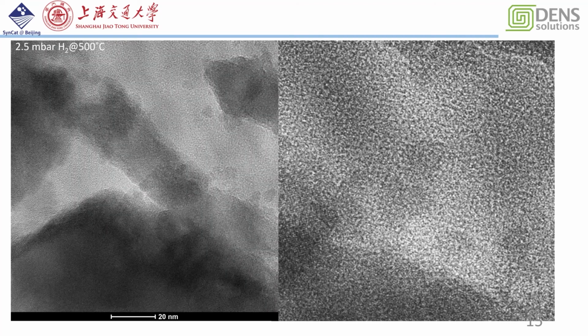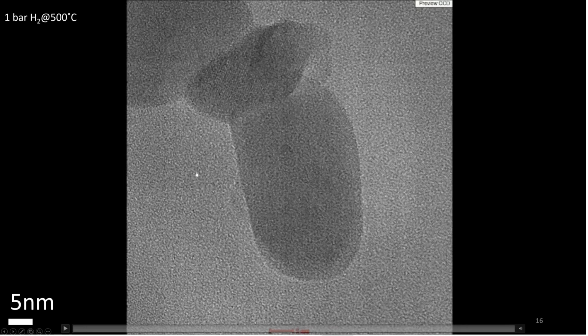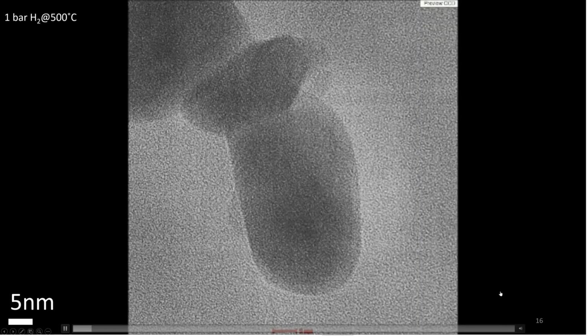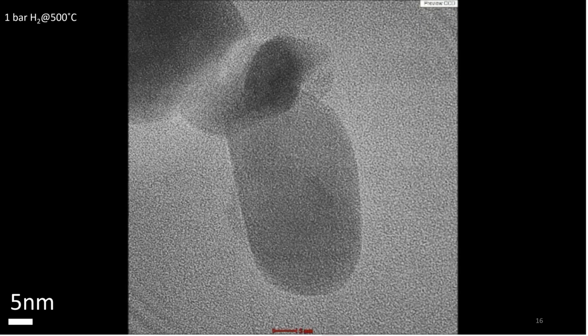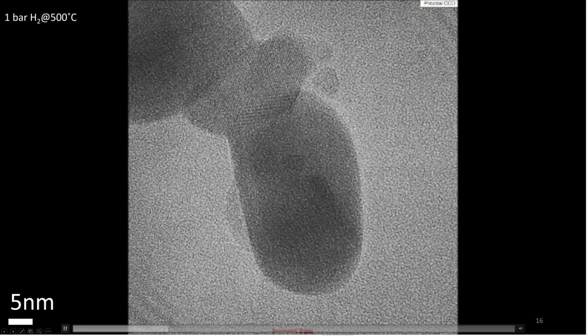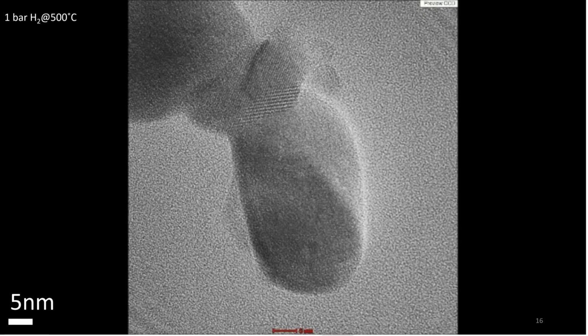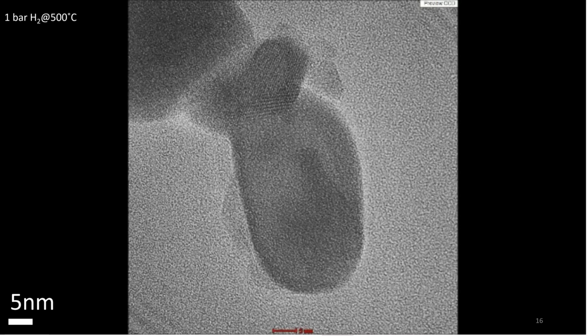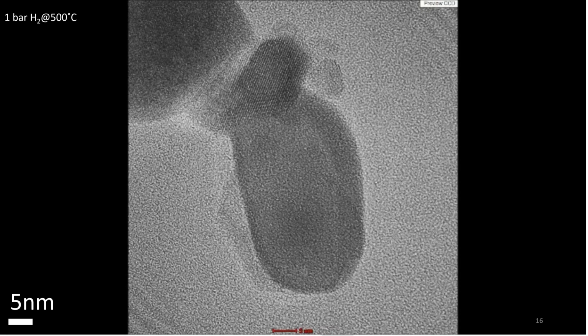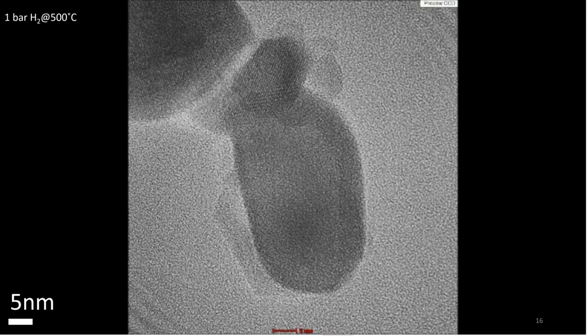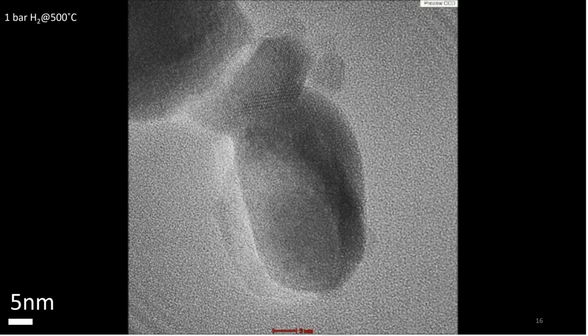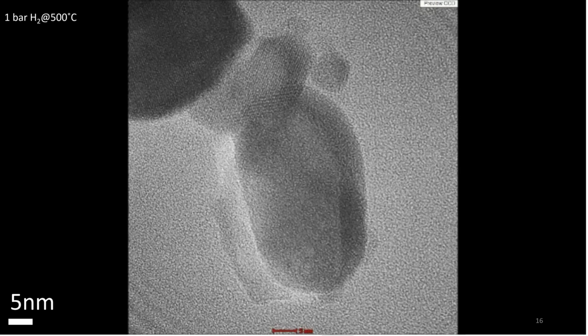If we see the complete transition process that happened at one bar and 500 degrees, initially the iron particle didn't change a lot, but during the reduction process a new phase diffused out of the parent particle, and afterwards the inside of the particle suffered a strong reconstruction process, and we can even see some explosion happening inside the particle.